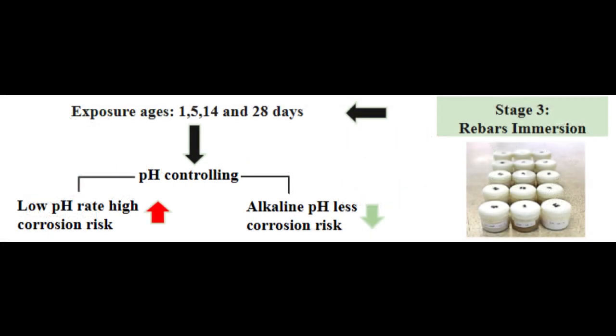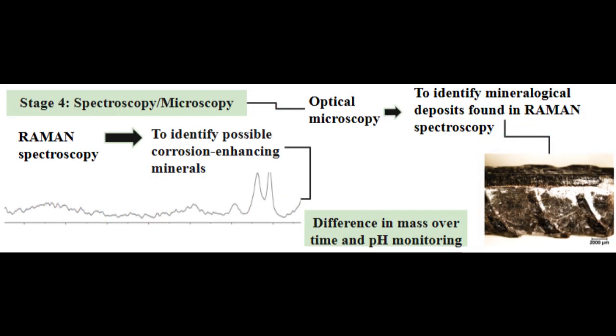Steel bars were exposed to these solutions through immersion, and both the initial pH and initial mass of the solutions were measured for subsequent analysis. Bar exposure was evaluated at 4 different ages: 1, 5, 14, and 28 days. At each age, both the pH and bar mass were re-evaluated. Bars that reached their exposure age underwent additional analysis to identify expected minerals, specifically those belonging to the apatite family.